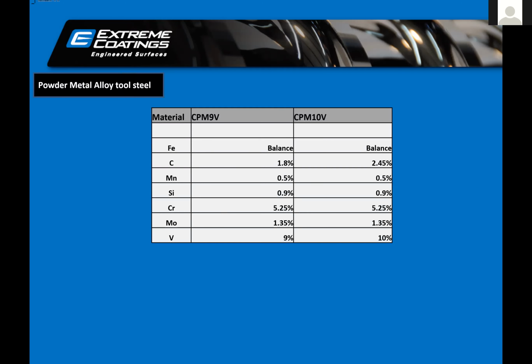Then the fourth kind we spoke about is powder metallurgy. This is very common in the US. This is the steel they use. If you see, the vanadium percentage is very high, 9%, 10%. Molybdenum percentage is also a little bit there. Chromium percentage is also there. So when it comes to steel, this is the best available. Beyond this, there is nothing available. So if you want to purchase a steel which is wear resistant to all three of these, then CPM 9V, CPM 10V is the best solution in terms of steel.